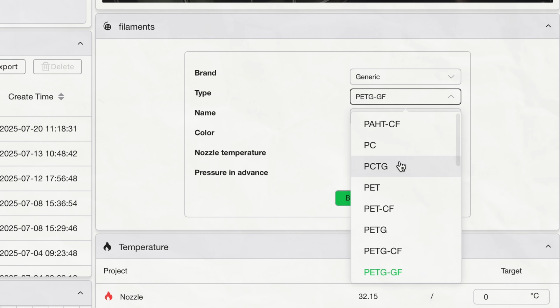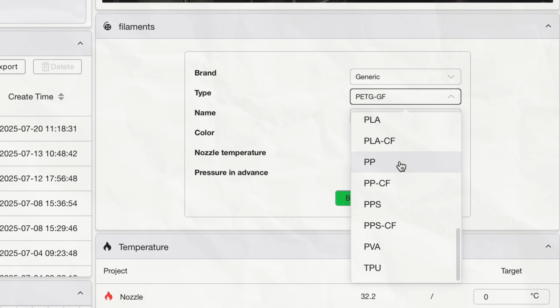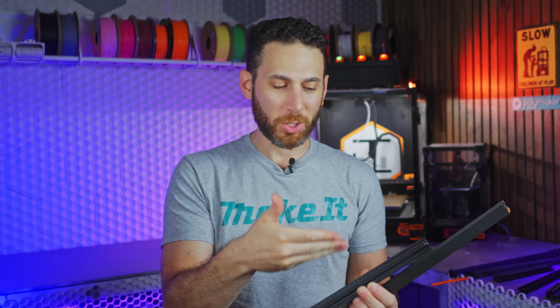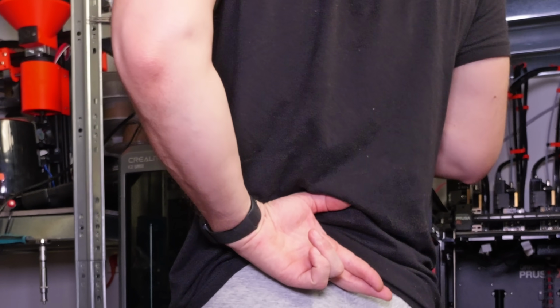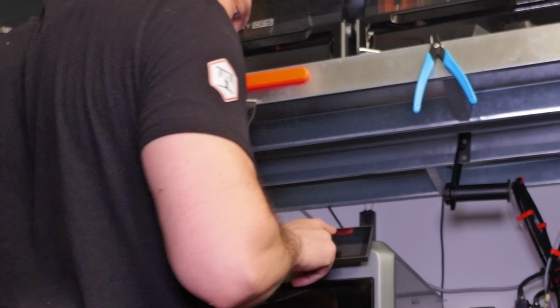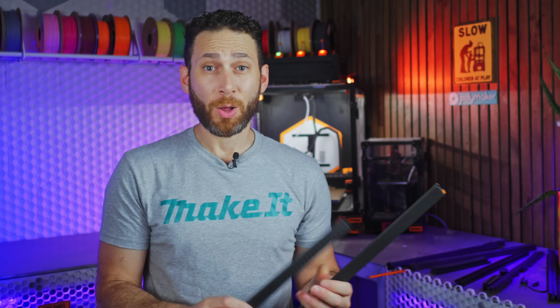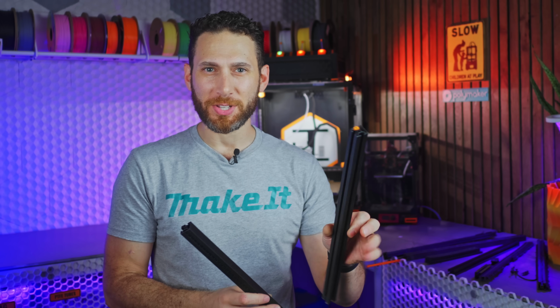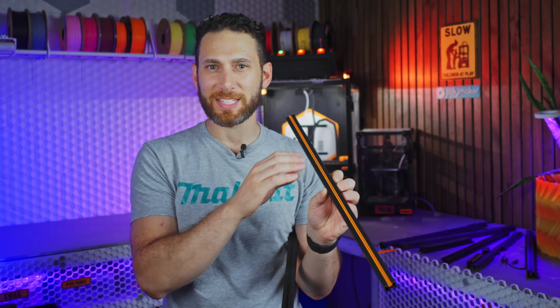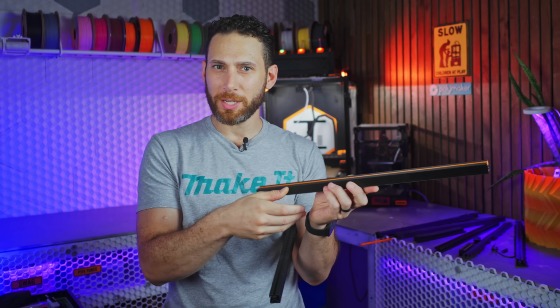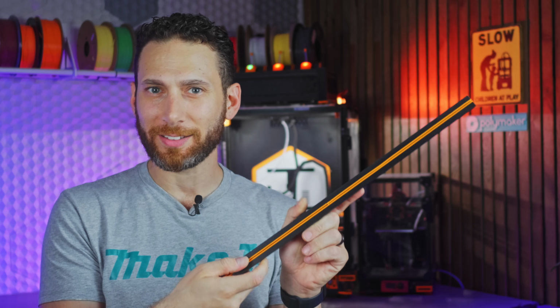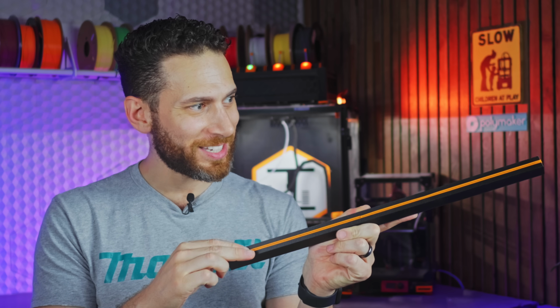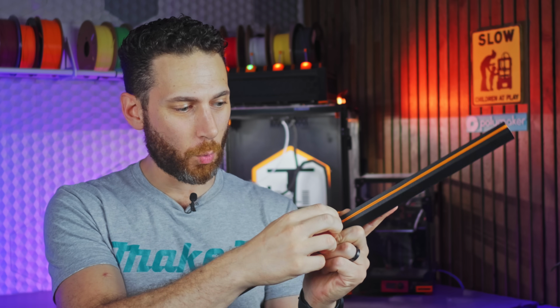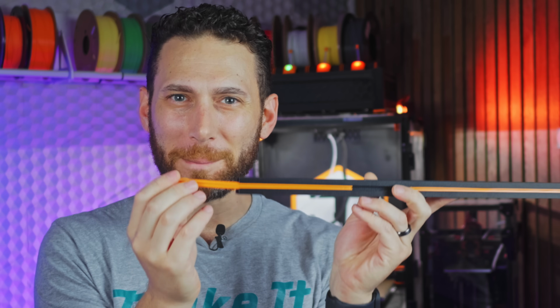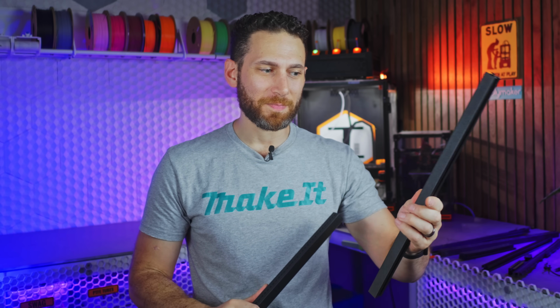The only annoying thing was that there's actually no way to select PAHT-CF on the printer, and it won't let you print unless the material matches the G code. So I think I ended up just telling it that it was PPS-CF, since honestly, they're close enough. Also, by the way, I think all my fears about the friction of adding in the sealing strips were probably unfounded, because once I got perfectly dialed in profiles, look at this, they actually slide in like shockingly well. And they fit beautifully. The only issue is build volume.